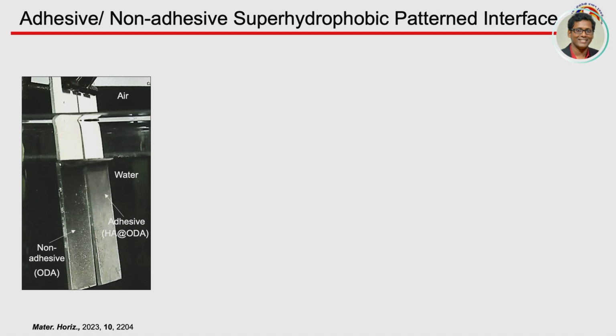So when I say adhesive and non-adhesive, it has not only the adhesion properties, it also gives another interesting property, the optical appearance when you are submerging underwater. Water is not going to wet the interface, but when you submerge under water, the light which is incident on this interface undergoes internal reflections, and because of that you see a shiny appearance.